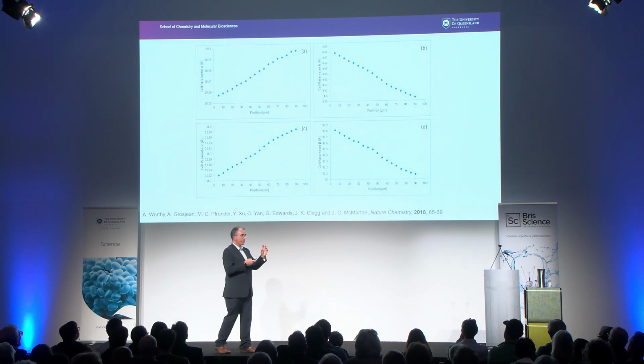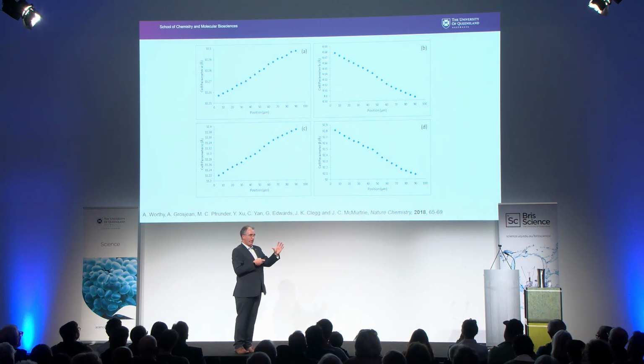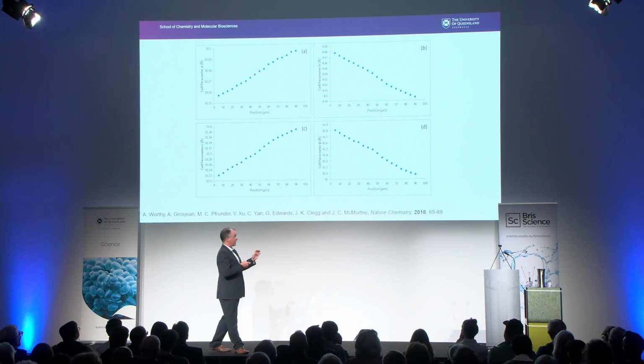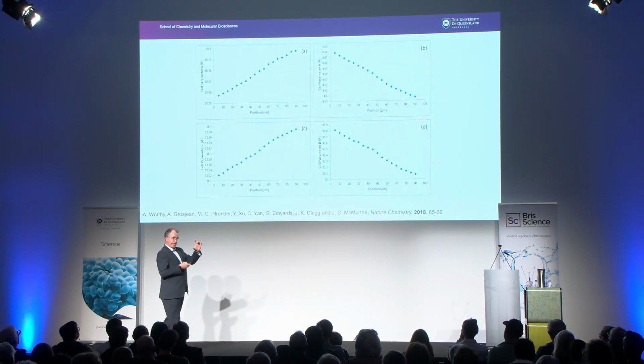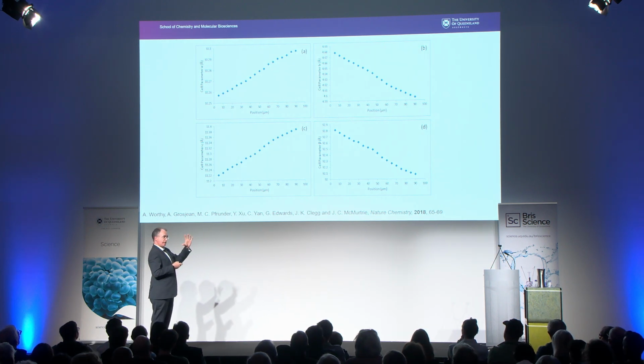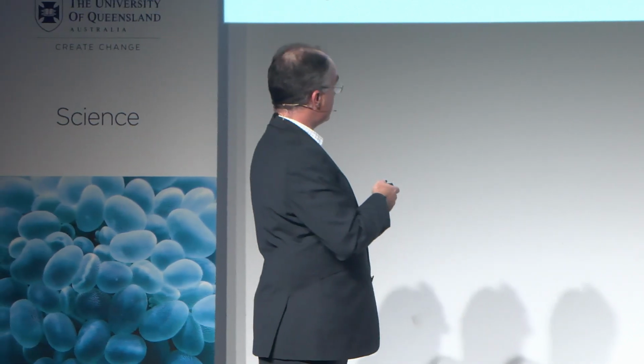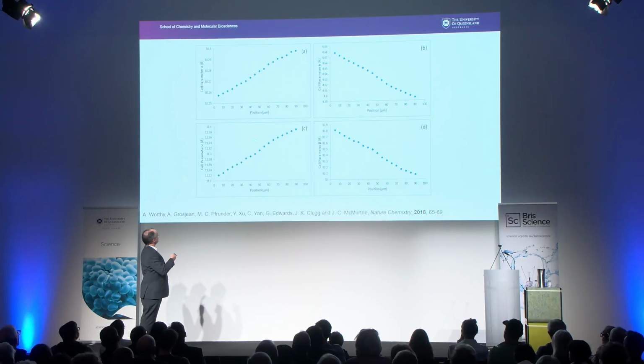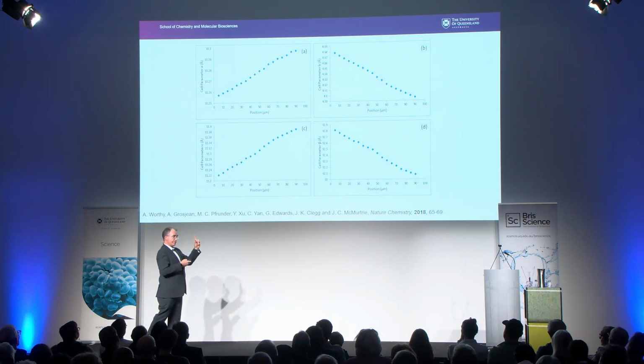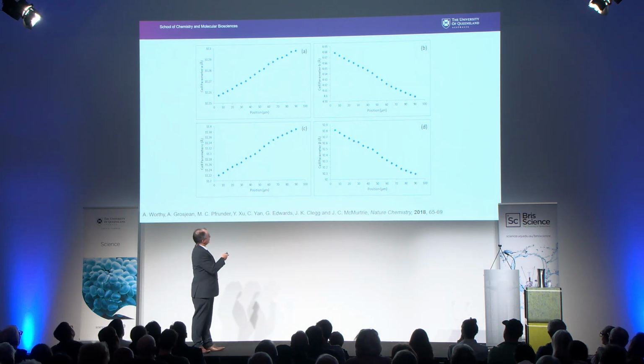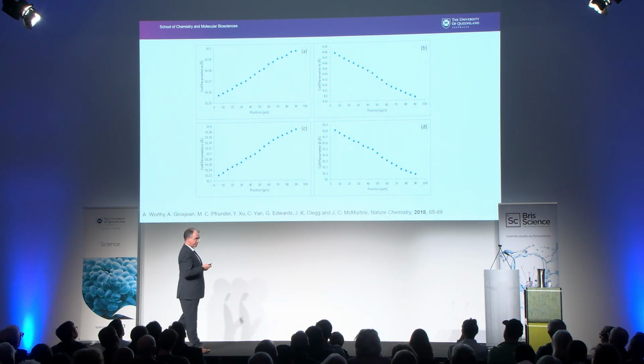And this is exactly what we expect from our theory of elasticity. Right? When we bend a beam, we expect contraction on the inside and expansion on the outside. So this is great. We're still in the elastic region of the crystal. We also see some other less expected changes. We see increases in the A and the C axes, which are the ones that are orthogonal to the B axis. And we see a decrease also in this B parameter.